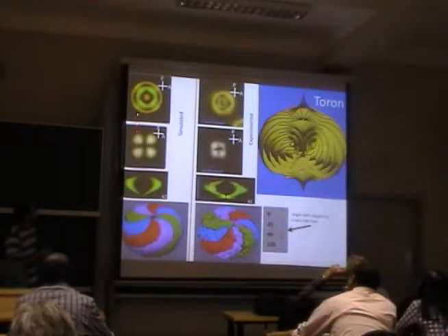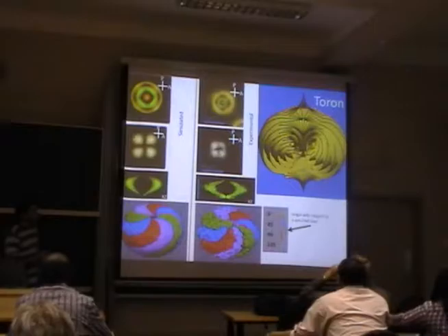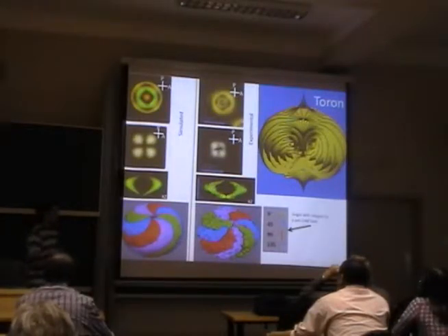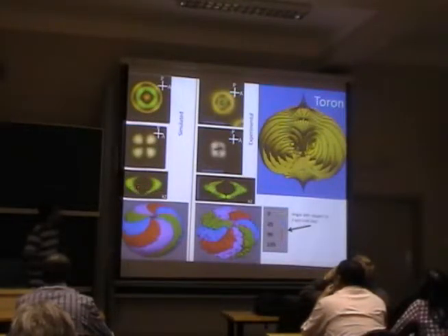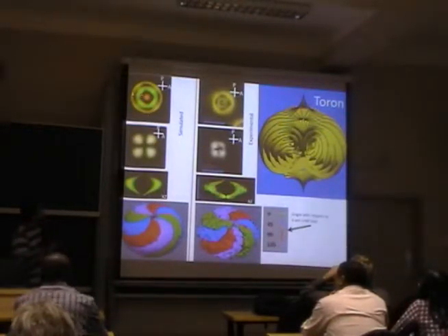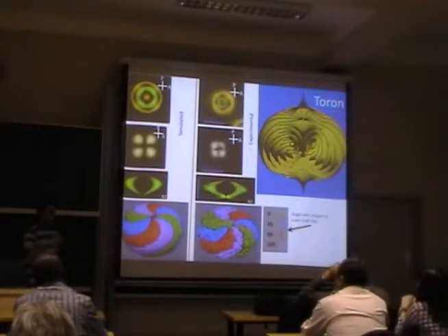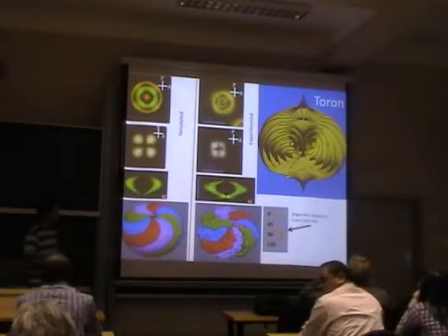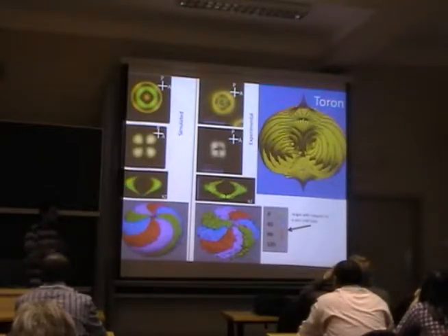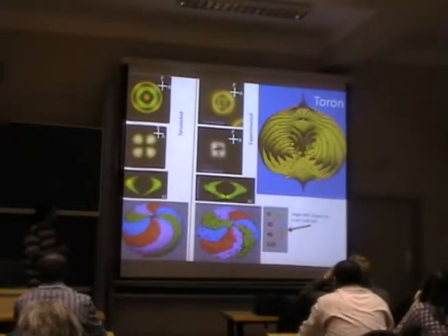So the difference between these two images is just the thickness of the sample. So there's more birefringence, and so you get more pretty colors. This image is a cross section, and it's what would appear if you take an XZ cross section through a toron, and looking for liquid crystal molecules that have twisted more in plane. And so the bright signal is from the in-plane molecules. So this is the center of the double twist cylinder, and here are the point defects.